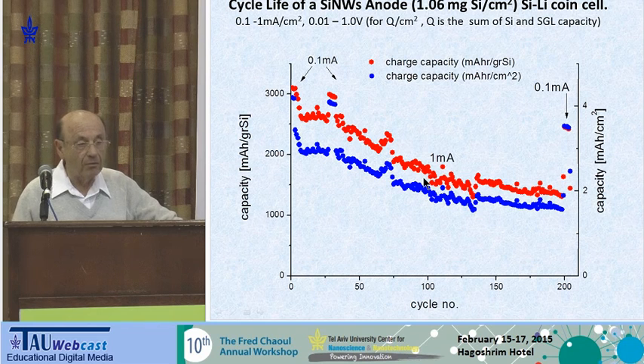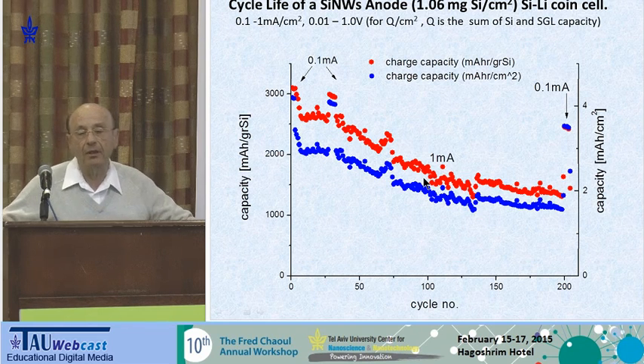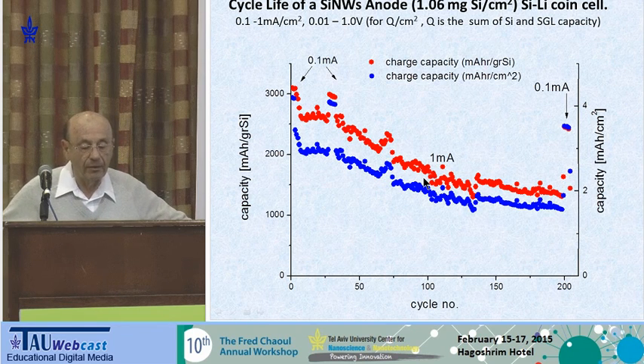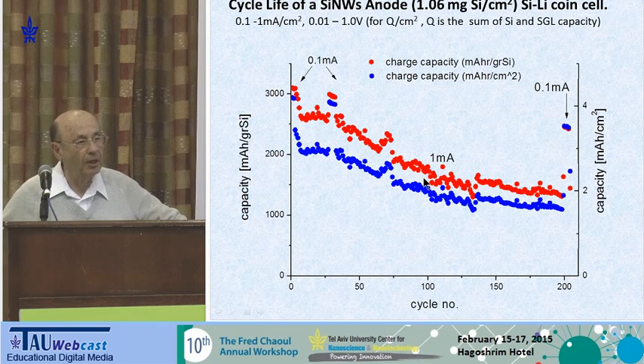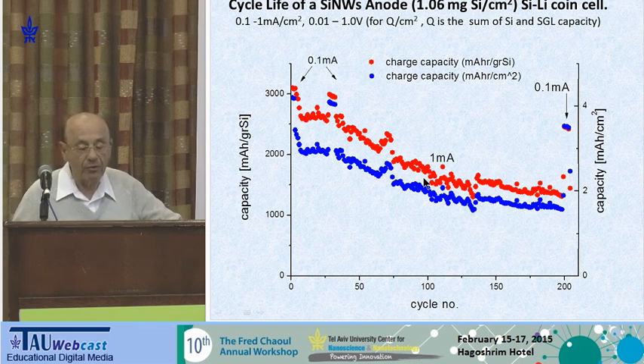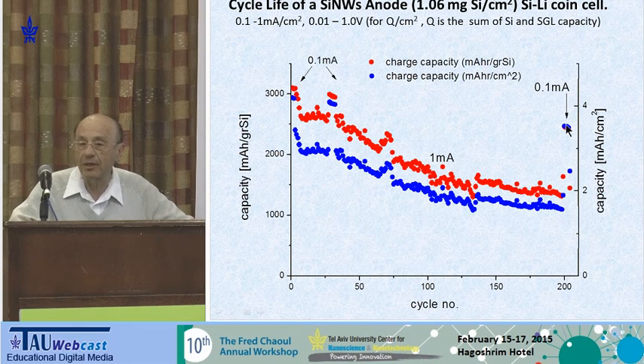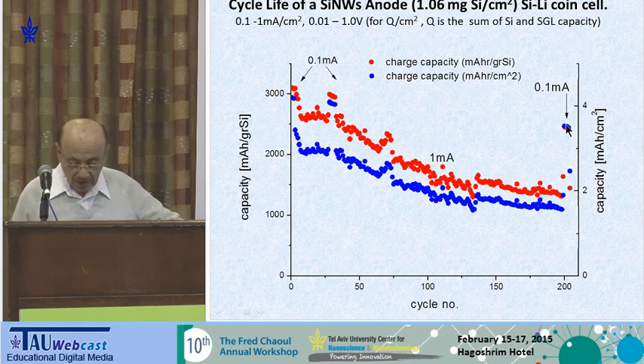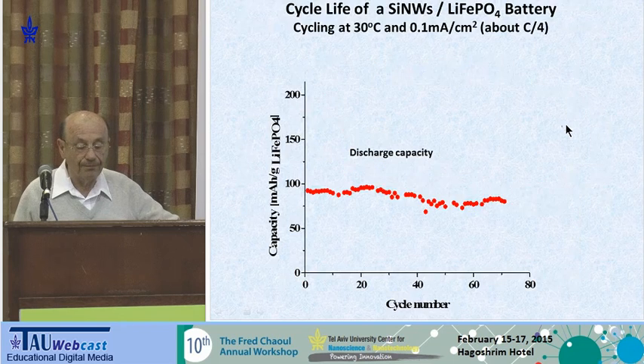So there are two options. One, what is commonly written in the literature, is that we have pulverization and loss of contact of the silicon nanoparticles or nanowires, and therefore we lost capacity. But we came to the conclusion this is not the case. When we reduce the current density to 0.1 milliampere, we got back the capacity, and actually here we lost, after 200 cycles, only 20% of the capacity. I think we can lose less.